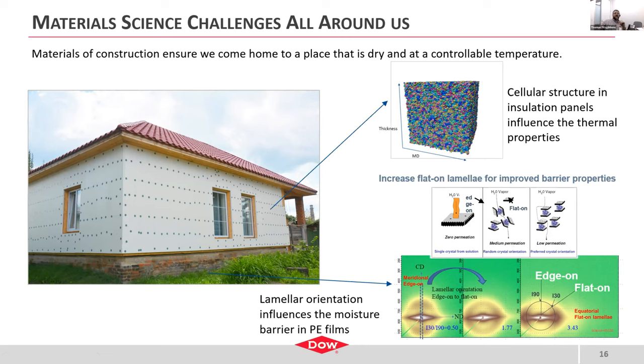So one thing that you can think to try and do to increase the moisture barrier is to get all of your lamellar crystals to lay in the same direction, forming a plate-like geometry parallel to the axis that the moisture is coming through. What we've done is we've developed a method to use small angle X-ray scattering and looking at polyethylene films to understand how to quantitate the amount of lamellae that are randomly oriented or edge-on lamellae versus the number that are flat-on lamellae, looking at the small angle X-ray scattering and various orientations of these polyethylene films.